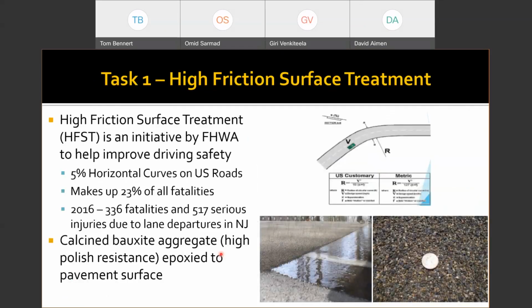We look at here's a product for safety called a high friction surface treatment. And this is something that is becoming popular for horizontal curves in trying to reduce fatality accidents of people actually, unfortunately, leaving the travel lane. And some really interesting statistics: there's approximately 5% horizontal curves in all U.S. roads. About 5% of all the roads make up these horizontal curves. But when you look at the rate of fatalities, it makes up 23% of all fatalities nationally. That's a significant amount of fatalities for a small portion of the pavement network around the country.